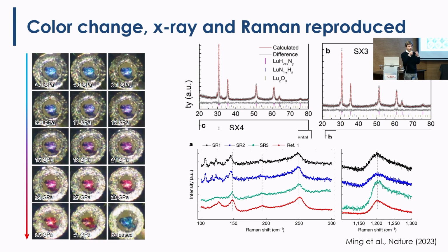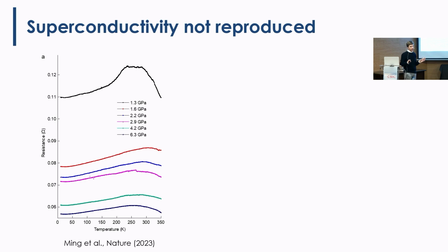Because with X-ray the lutetium is huge, you don't see the hydrogen, so you can know only with X-ray where the lutetium are, okay? So the lutetium seems to be in an FCC. If you have lutetium metal, it's FCC, so somehow not a big novelty, okay? So the Raman is also consistent in this paper with the other one by Diaz. So you have peaks at high energy, 1,200 cm^-1, and then some peaks at 250 and some below, okay? But the resistance, no trace of superconductivity in this experiment, has not been reproduced.